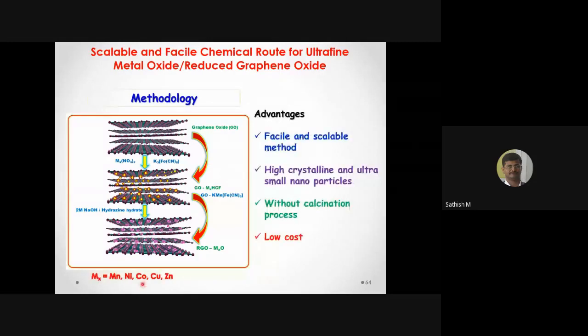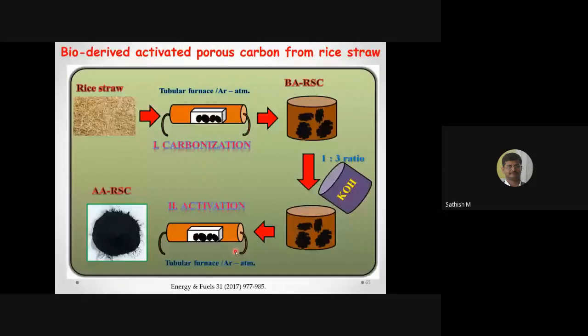So we explored this for manganese, nickel, cobalt, copper, or zinc. Most of the cases end up with metal oxide. In one or two cases we end up with hydroxide. I think in the nickel case we end up with nickel hydroxide, not nickel oxide. Okay, so the nickel hydroxide as it is can be used as a pseudocapacitive material.